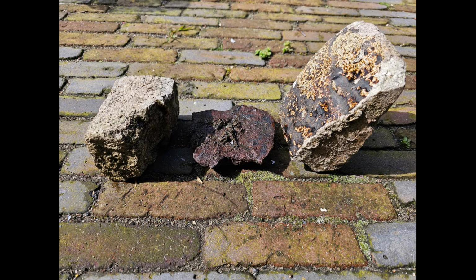From the same slag deposit as the fully liquefied ingots were found, clay blocks have also been retrieved that can best be identified as parts of remelting furnaces. These are most likely little doors that were cut out of the clay furnace when the clay was still wet to aid in the extraction of the ingots when the smelt was over. A highly glazed surface coating on these clay blocks shows that they have been subjected to extreme heat, but the glaze looks more like an ash type of pottery glaze and not so much a bloomery slag type of glaze.